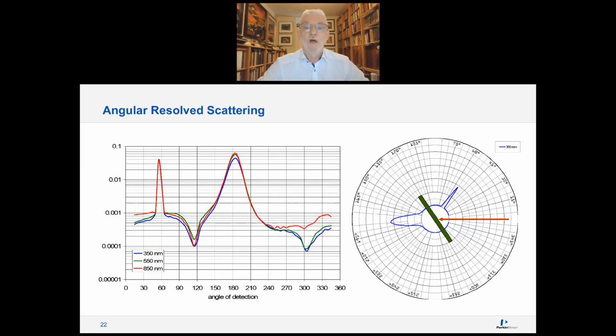Another example for measuring with a TAMS or an ARTA is angular resolved scattering. This is a simple sample which has nothing to do with solar glass. However, it is a diffuse surface of a glass, sandblasted glass. What you see here is a profile, a distribution which is measured just at single wavelengths using the ARTA. You can also do complete wavelength scans, but this is just a few wavelengths.